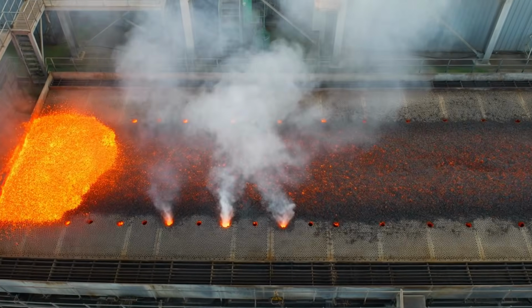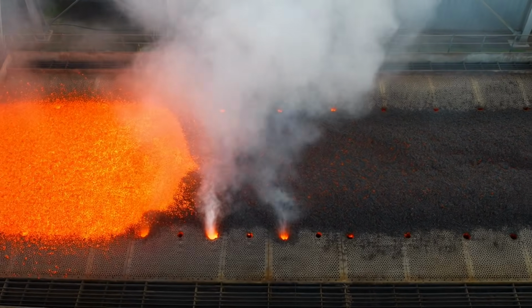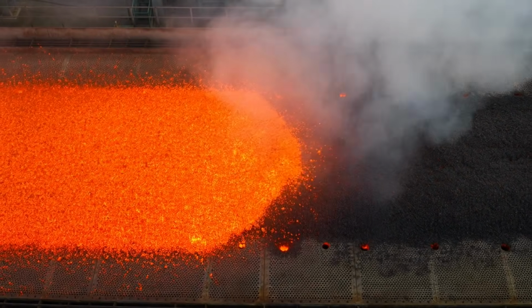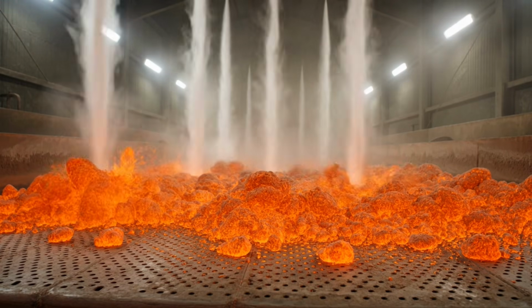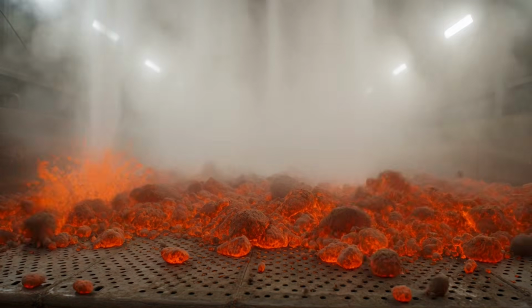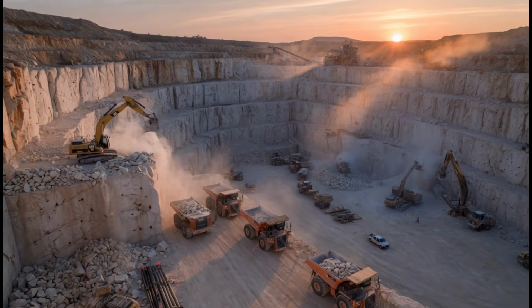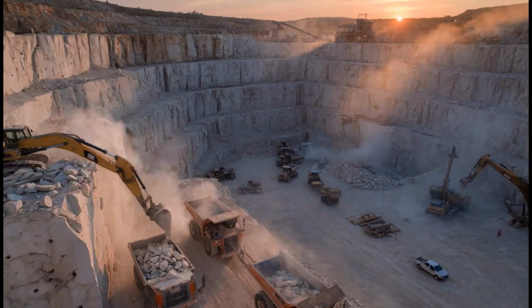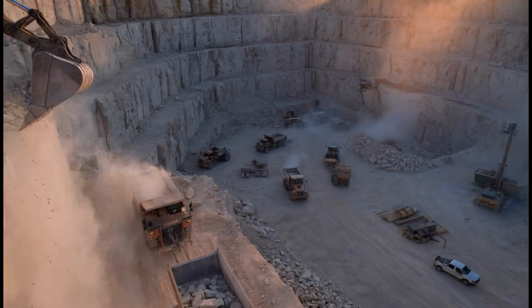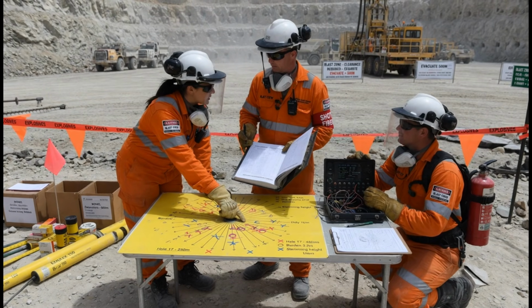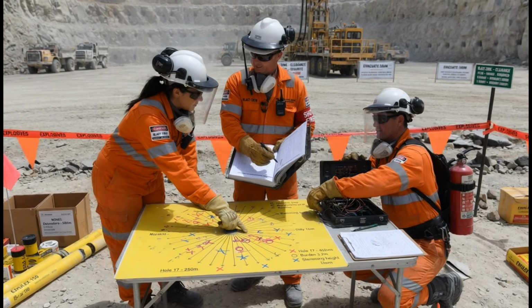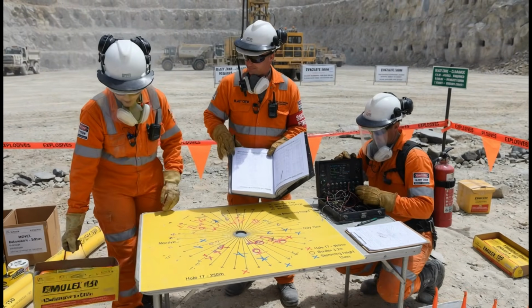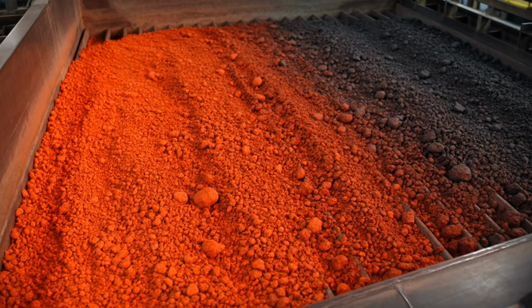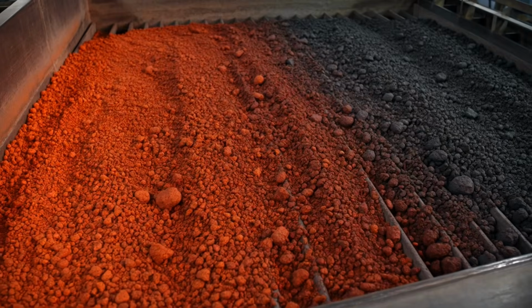This single nodule, glowing from residual heat within, this small lump is what becomes cement. You can't grind 1,000-degree material, so the clinker drops onto a cooler, blasted with cold air from below. From 1,000 degrees to 100 degrees in minutes, that rapid cooling locks in the clinker's chemical structure. Orange to cool gray, left to right, 900 degrees of temperature in a few meters.